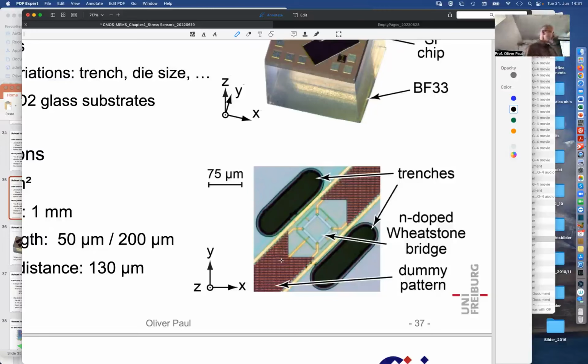But metal is a plastic material, and when you expose metal patterns to 2000 bar, actually 600. He only had a setup up to 600 bar. It just deforms plastically, partly. This is very high pressure for metal lines. And so having something plastically deformed near the sensor meant that the offset of the sensor was also changed. There was a residual stress that changed with the number of cycles that were applied. And then as a function of temperature, higher temperatures, it was worse. And so he learned that actually one should better remove those dummy patterns.